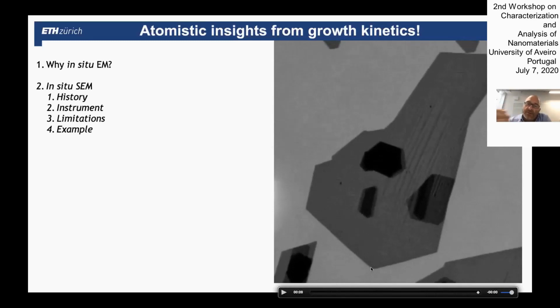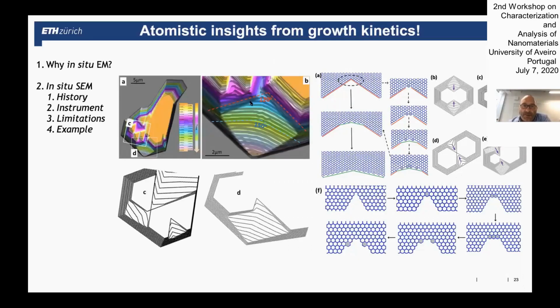And by just looking at this, also we don't have atomic resolution, but the time is our friend. So we have this additional variable of the temporal evolution. We could actually really study what happens during growth when this concave angle is getting filled up very fast, and how this concave angle that is formed by the zigzag edges of the two approaching grains is changing.